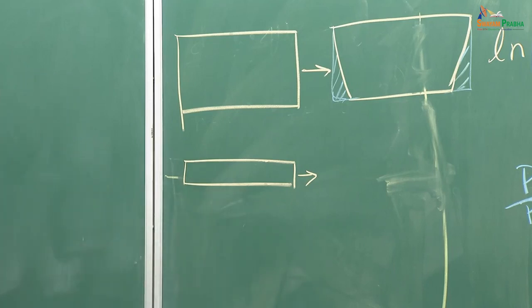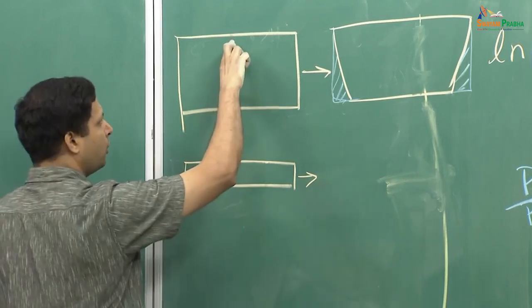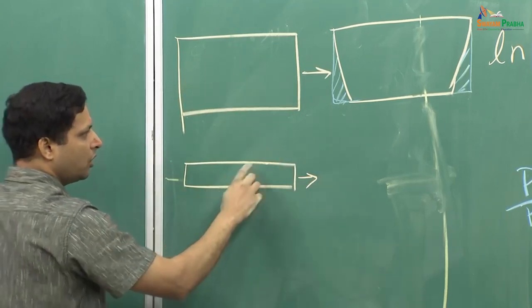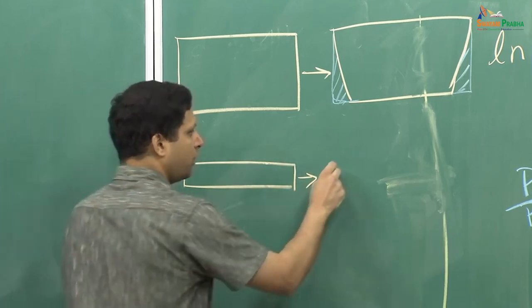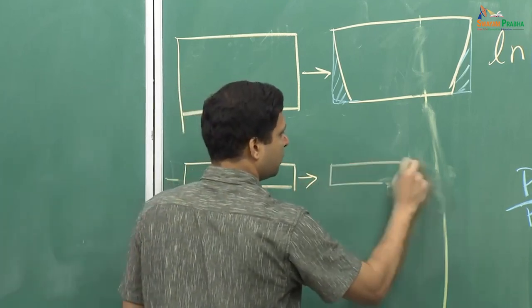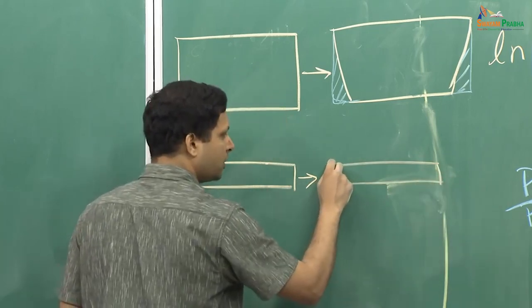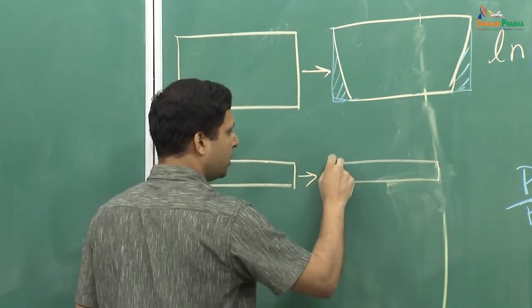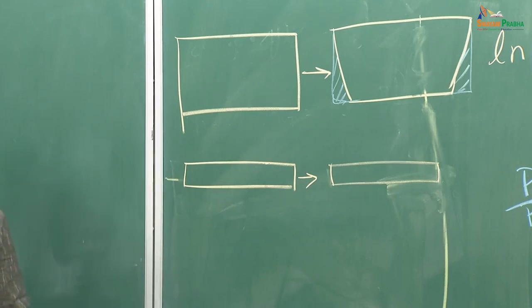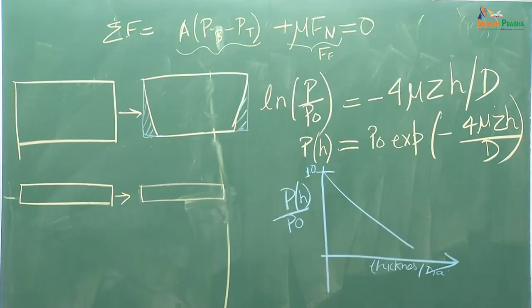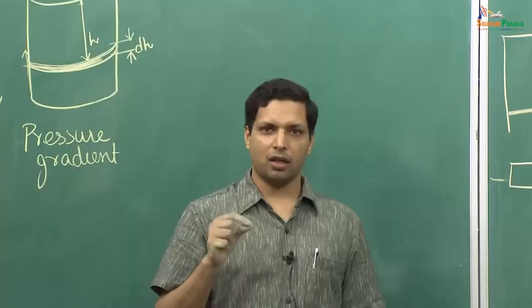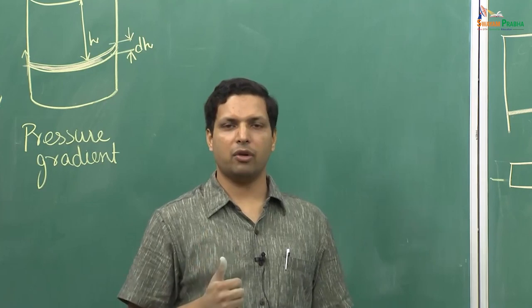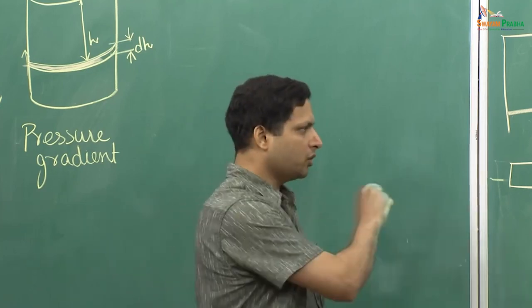We have seen that whenever you apply a piston and pressure, there will be a pressure gradient, which leads to density gradient and shrinkage. One way to address it is already shown here: if the component is very long in the z direction, there will be a larger chance of shrinkage. If you keep it short, the shrinkage would be so small it may be within the tolerable limit. That is one reason why in powder processing we use only 2.5 dimensions — in the third dimension you do not have much height of the component.